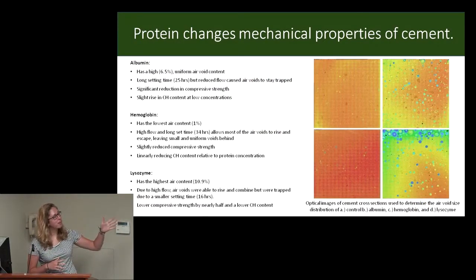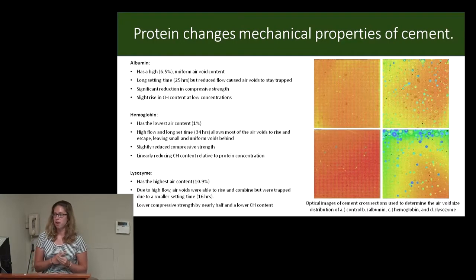Anyway, we put these into cement to test the changes they made in the cement. For albumin, we saw a high increase in the air content. As you can see, it went up to 6.5%, which is far greater than normal cement. It also increased the setting time and decreased the flowability, which allowed the air voids made to remain trapped in the cement.